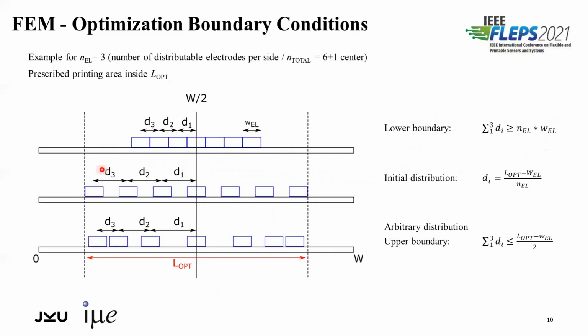I start every optimization with a neutral uniform distribution like this, where the initial distances are calculated by this term here. On the bottom, you see the boundary condition for the electrode distances for every following distribution during the optimization. In the formula, the factor 2 comes from the fact that the distribution is, of course, symmetric around a center electrode, and we only have to calculate the distance shifts for half the number of electrodes to save some computing time. And this works, of course, only for a uniform temperature distribution.